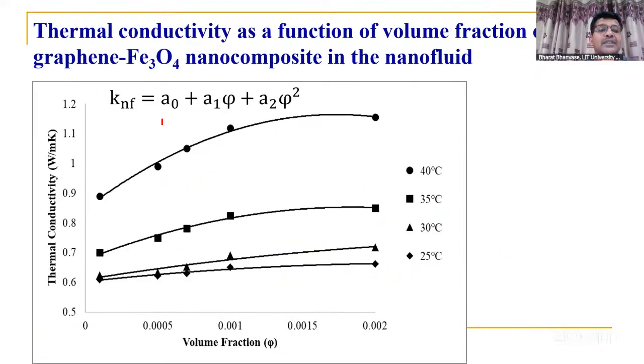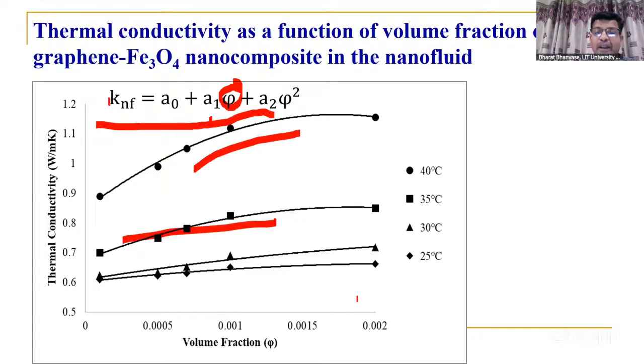This is some empirical statistical analysis we have carried out. Based on the experimental data, we generated this quadratic polynomial, thermal conductivity as a function of volume fraction of nanomaterial. That is created, and we observe it is well fitted for all the data at different temperatures.